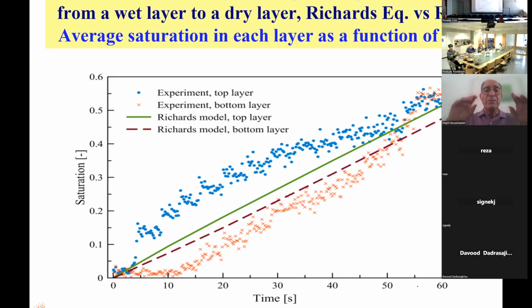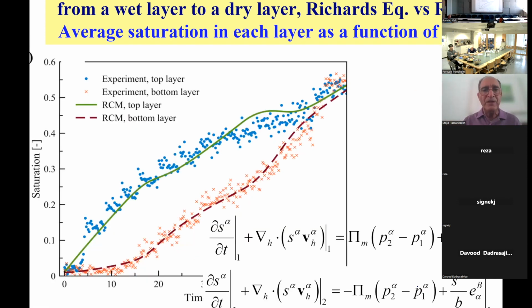I must tell you that we were able to get the porosity as a function of depth because we did the imaging, and we defined 14 sublayers for each layer for our modeling with Richards' equation. We really put in the real value of porosity. We also constructed PCS curves for those sublayers. So we broke it into 14 sublayers. That was also our numerical grid, and we didn't get any fit. Whereas when we use our equations, you can get a very nice fit.